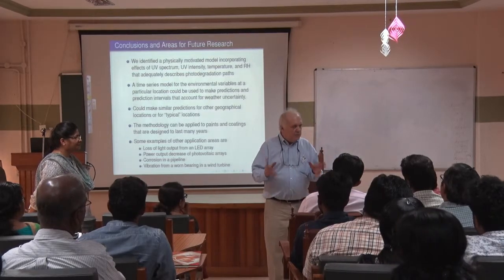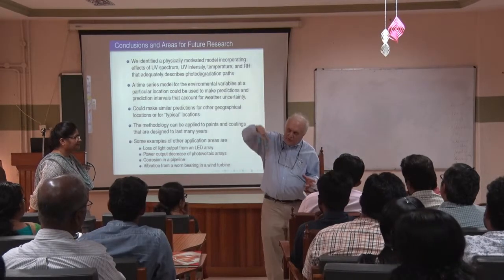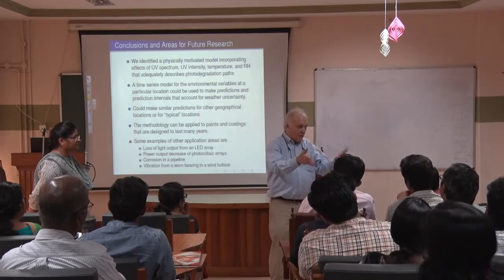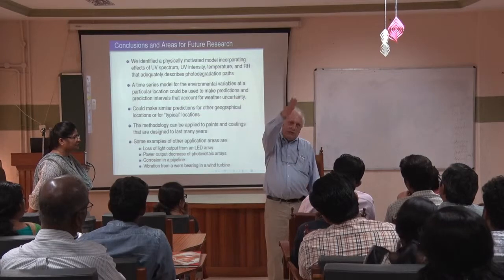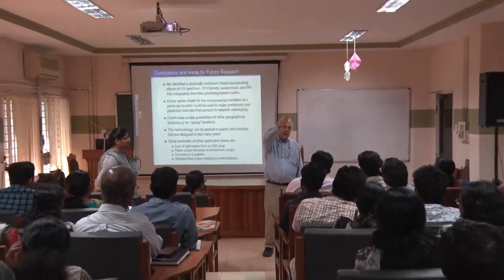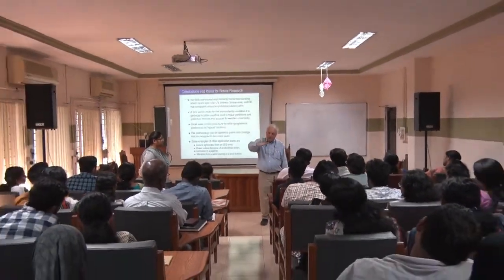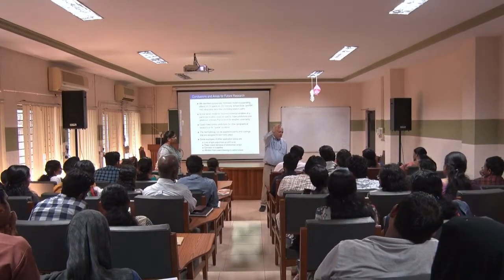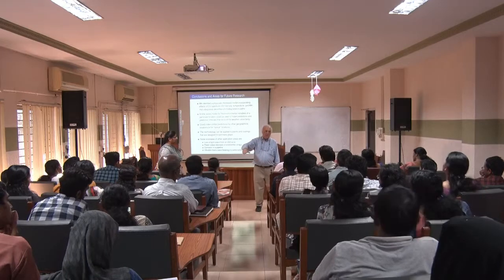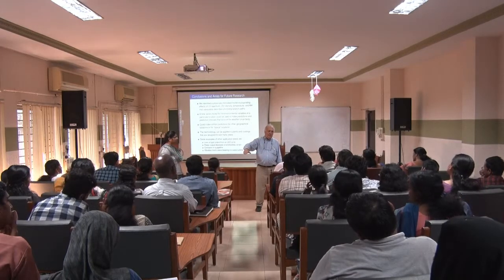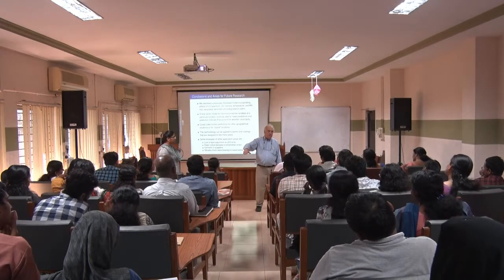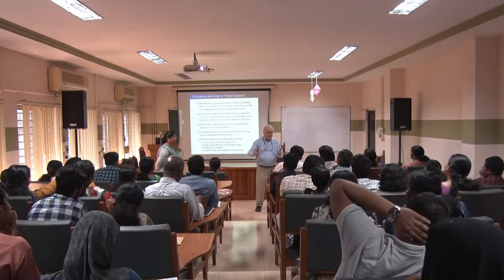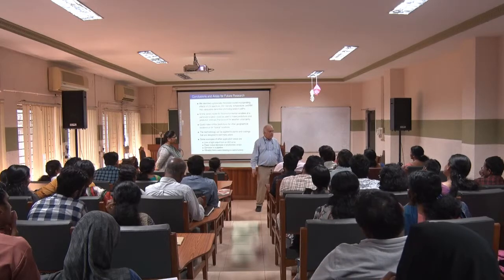In the case of humidity, we saw this kind of behavior that was purely empirical. We said, oh, I think we can fit that with a quadratic curve. And the other one, we saw the damage going down exponentially like this for the quasi quantum yield and sort of approaching zero, the amount of damage approaching zero as the wavelength gets bigger. We said, oh, that was a nice exponential function. So that's what we fit, but we also saw that used in the literature as well.